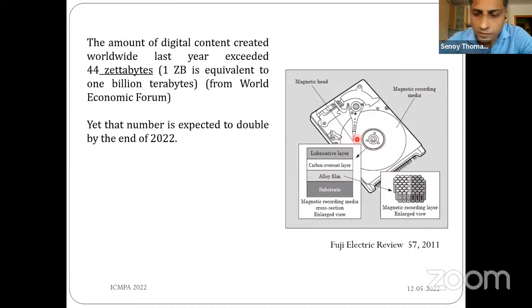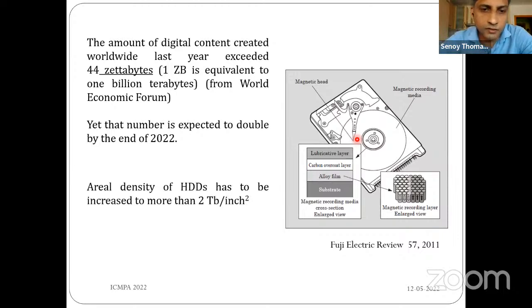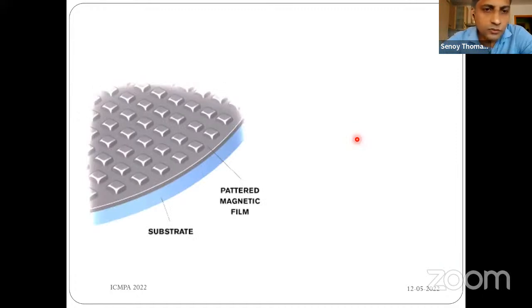So, due to the increase in the volume of digital content which we create in our day-to-day life, one has to go for hard disk drives with higher areal densities, and current requirements force us to increase the areal density of hard disk drives to more than 2 terabit per square inch. Several strategies have been developed to address this issue, and one such strategy is to use the so-called bit patterned media, where one lithographically defines magnetic islands on top of the disk. Each of these islands acts as a single bit, and depending upon the magnetization direction, one could define the digital zero or one.